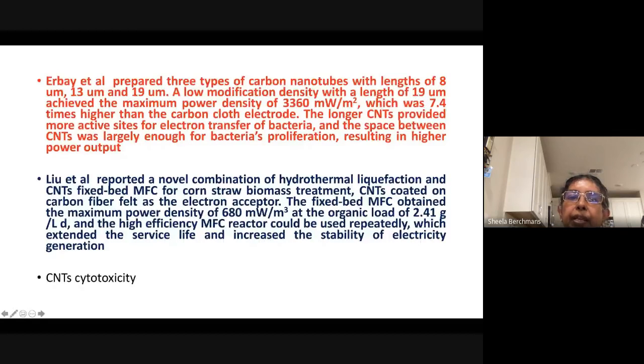In another report, a novel combination of hydrothermal liquefaction and CNTs fixed bed MFC for corn straw biomass treatment was discussed. CNT is coated on carbon fiber felt as the electron acceptor. The fixed bed MFC obtained the maximum power density of 680 milliwatt per meter cube at the organic load of 2.41 gram liter per day, and the high efficiency MFC reactor could be used repeatedly, which extended the service life and increased the stability of electricity generation.